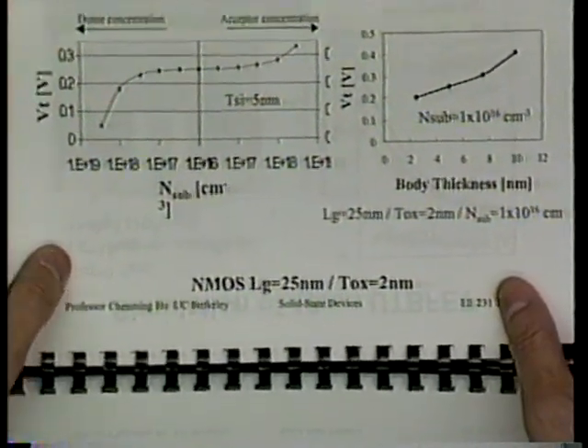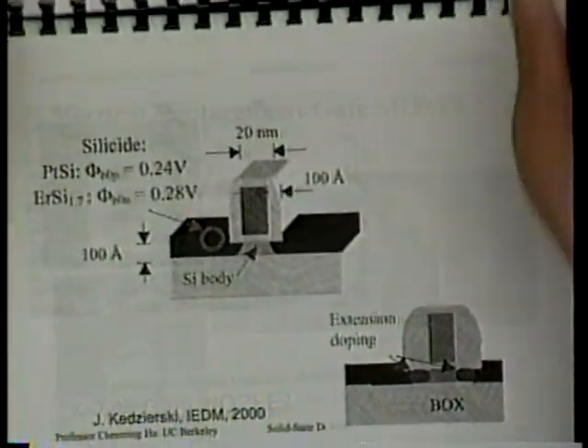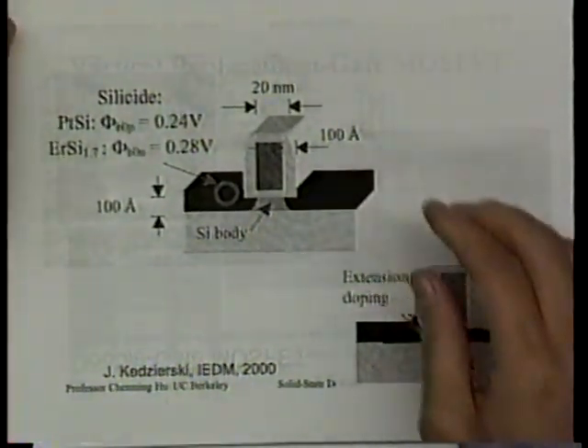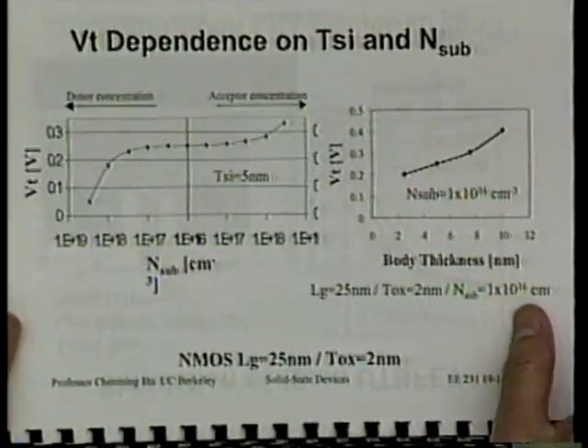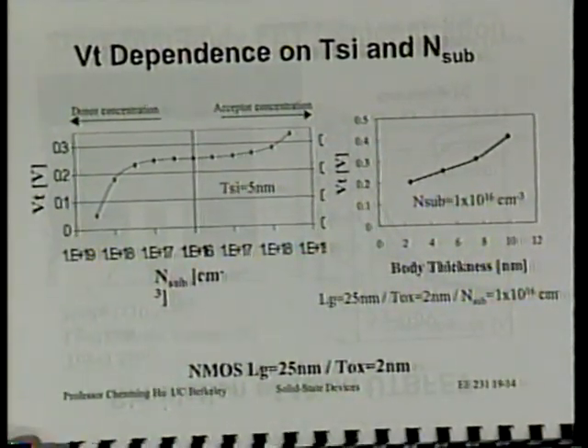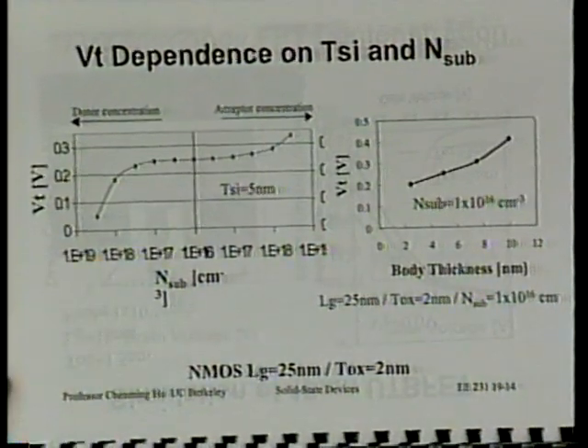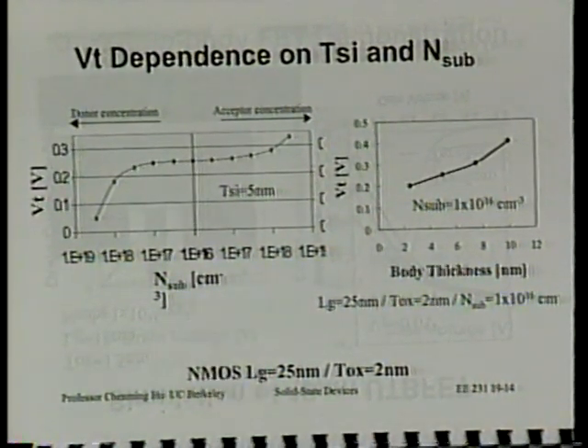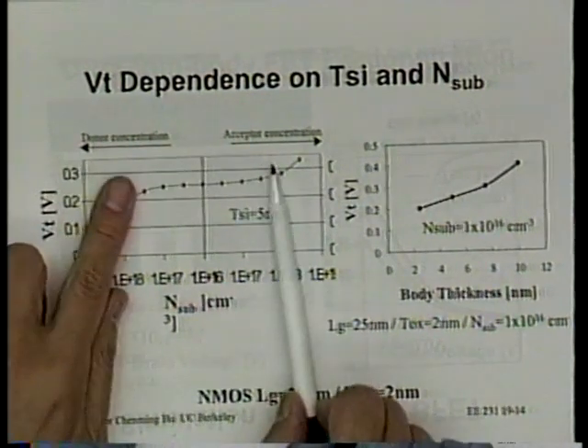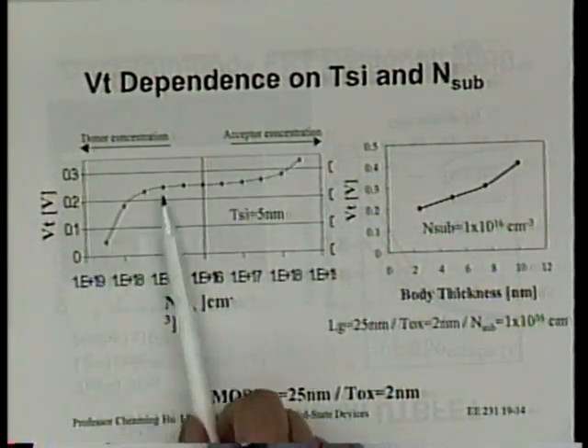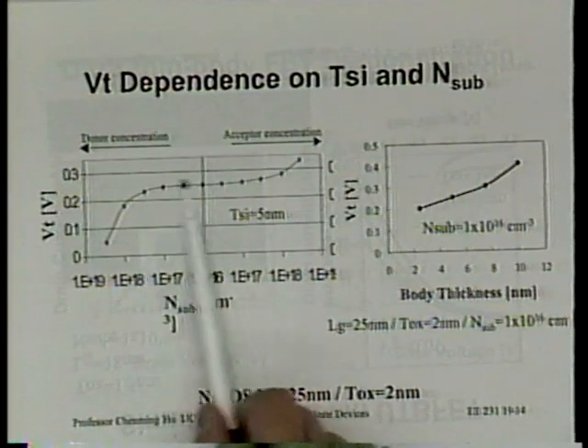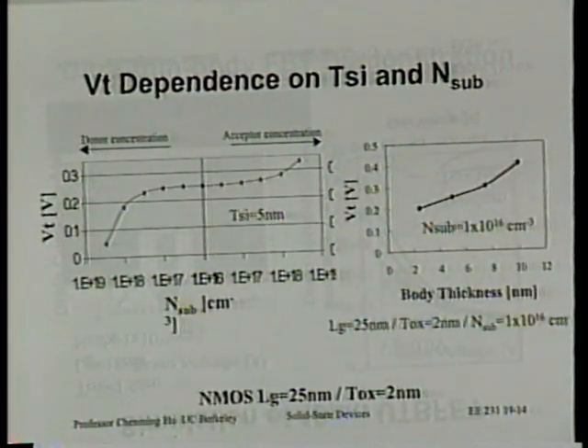Well, I will not go through the other slides. So any questions about this ultra-thin body device? Well, maybe there's one slide I will go through with you. So look at this VT dependence on silicon thickness and substrate doping. First, on the substrate doping concentration. Did you notice that over a wide range of doping concentration, the VT is very insensitive to the doping concentration? Right? But this is because if the silicon film is thin, you just don't have that many dopants. So this is how you beat the so-called dopant fluctuation.